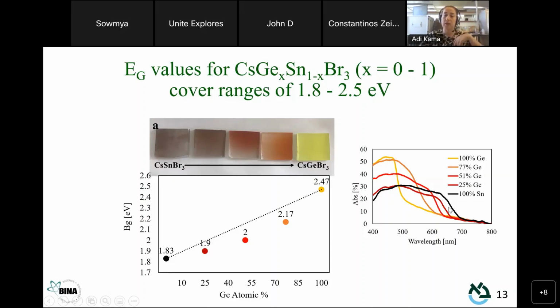And from the optical absorption, we could calculate the band gap that correlates well with literature for the pure compounds, 1.8 for the pure tin and 2.5 for the pure germanium. And the 3 compounds have a tunable band gap in between those 2 values.